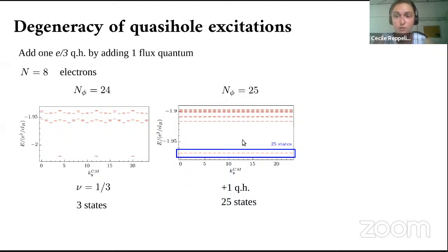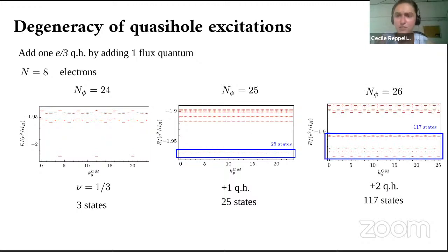Its main feature is that I still have a gap, but now the ground state, instead of being 3-fold degenerate, has a degeneracy of 25. And if I add two quasi-holes, I have a much more complex spectrum, still with a gap, and actually 117 states below the gap.